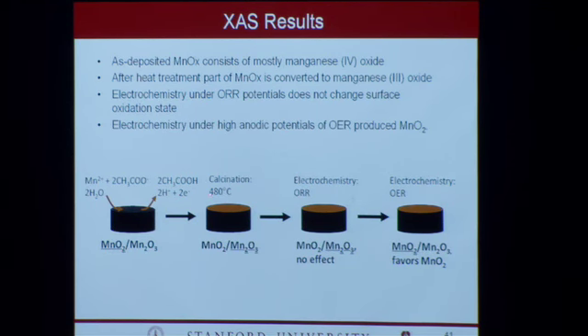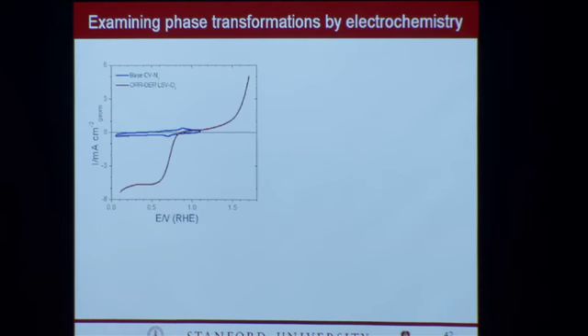After we heat it to this specific temperature of 480 degrees C, we've been able to enrich the Mn2O3 phase. After doing electrochemistry during oxygen reduction reaction, we don't see much of an effect from the as-synthesized sample. It's predominantly Mn2O3. But once we take it out to oxygen evolution potentials, which are very oxidizing, we actually see a change in the phase to MnO2. So this tells us that there's phase transformations. It's basically a different manganese oxide surface during the oxygen reduction fuel cell reaction versus the oxygen evolution reaction.